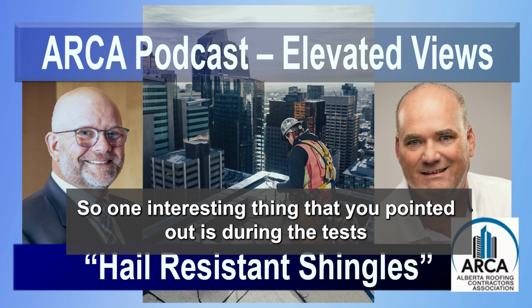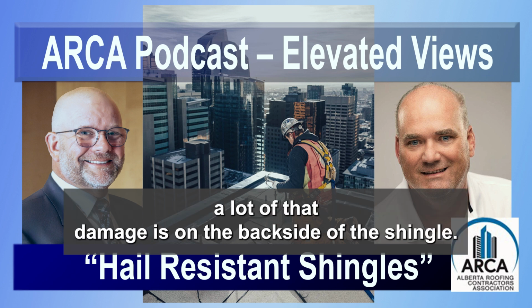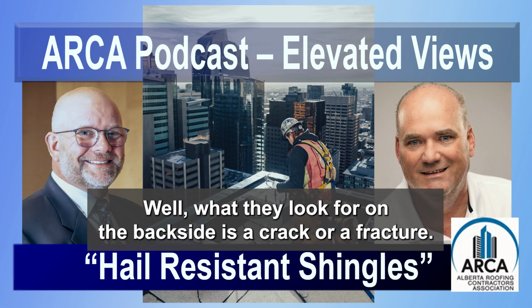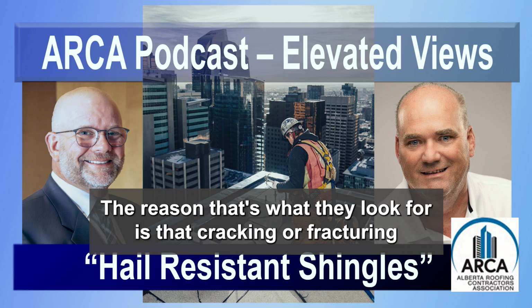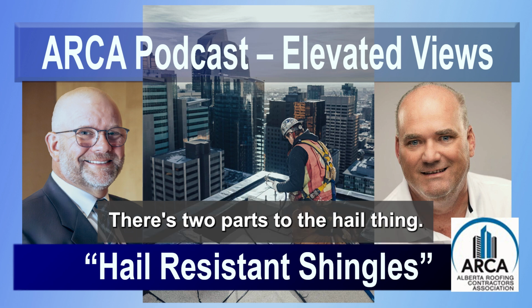One interesting thing that you pointed out is that during the tests, and obviously probably for in situ jobs that have already been done, a lot of that damage is on the back side of the shingle. It's not on the front of the shingle. What do you notice on the back side? Well, what they look for on the back side is a crack or a fracture. The impact hits the shingle and it actually cracks or fractures the fiberglass mat through to the backside. The reason that's what they look for is that cracking or fracturing now leaves a hole, which then can result in a leak.